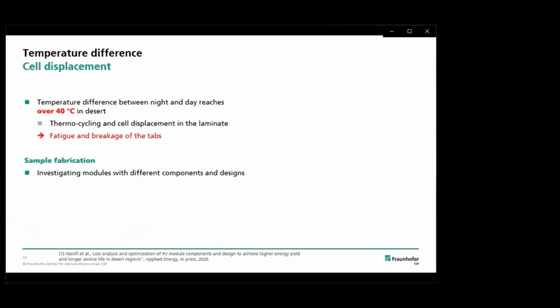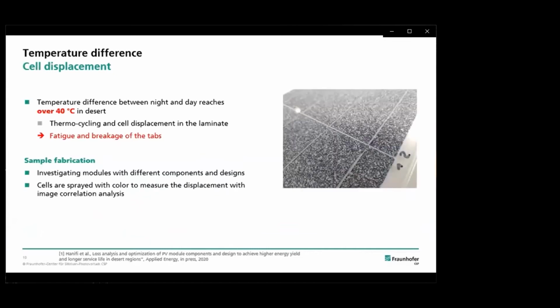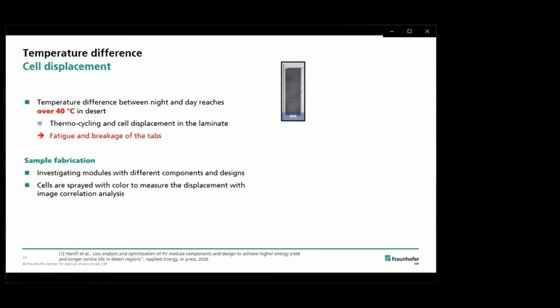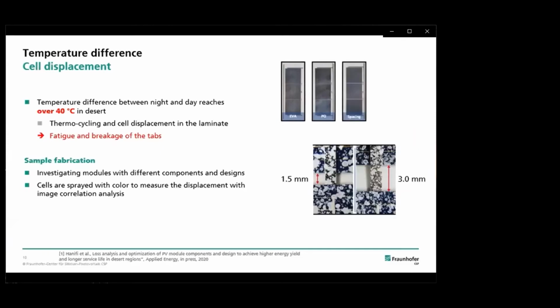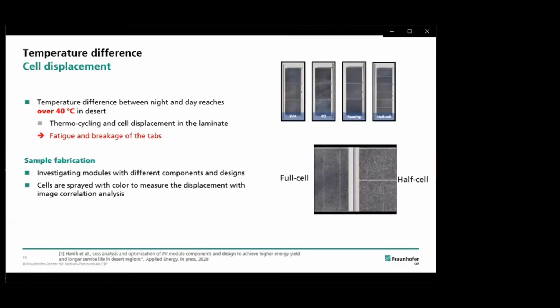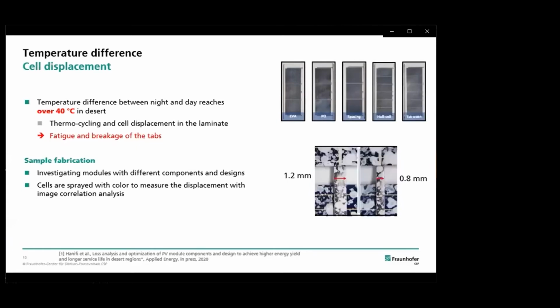and here we want to present some results which we did on different tab interconnections, and for that we use different components and designs of PV modules, and in order to see the cell displacement within the module, we sprayed it with color to measure the displacement with an image correlation analysis. And here you can see some examples. We used EVA, we used also polyolefin as an alternative. We changed the spacing between the cells, and we also moved from full cell to half cell design, also changing the tab width, which could also improve our optical performance of the PV module.